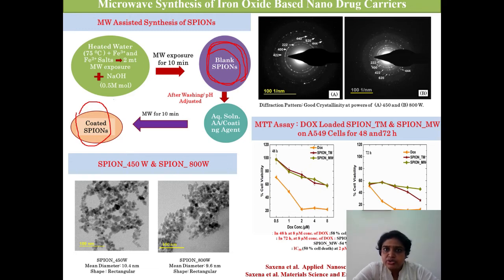Here I have shown the XRD pattern of two SPIONs which were synthesized at different power. The first one is at 450 watt and the second one is at 800 watt. In addition, the size of the SPIONs, that is superparamagnetic iron oxide, was very uniform, and this is again an added advantage of microwave synthesis because they are of very much use as a nano drug carrier.